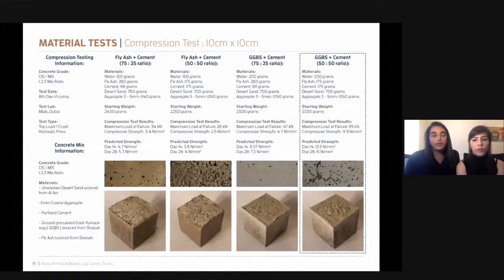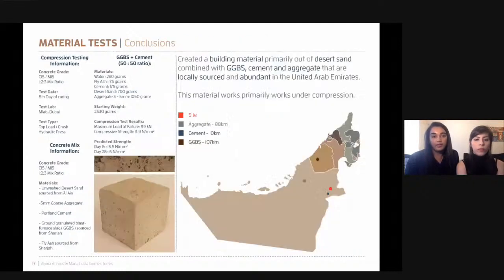After our initial evaluations, both fly ash and slag were combined with cement using different ratios in order to create our samples using the C15 mix ratio for compression testing. Each 10 by 10 sample was left to cure for 7 days before we did the test, and sample four, which was comprised of a 50-50 ratio of GGBS and cement as the binder, along with local desert sand, achieved a compressive strength of 9.9 newtons per millimeter squared at day 7 and was predicted to reach a 15 newton per millimeter squared compressive strength after curing completely.